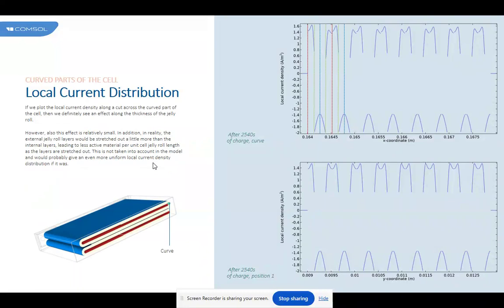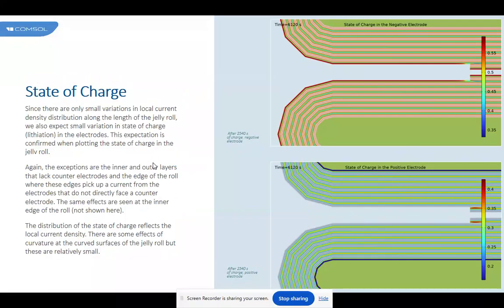In addition, in reality, the external jelly roll layers would be stretched out a little more than the internal layers, leading to less active material per unit cell jelly roll length as the layers are stretched out. This is not taken into account in the model and would probably give an even more uniform local current density distribution if it was.